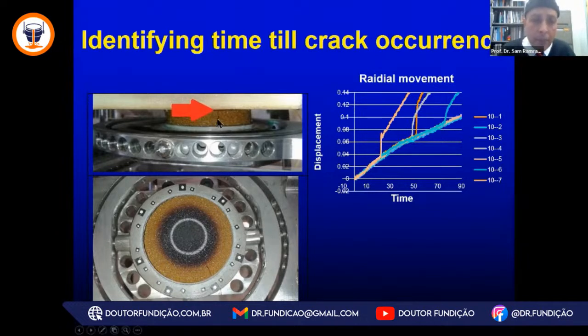Certainly, I mentioned the ideas of cracking. Here I'm showing you the crack propagation radially, and on the top view of the specimen, here is that crack. We can tell from the thermal distortion where we see this inflection on the curve, the time that that crack occurs. The main thing that we have to understand is not the fact that the specimen can crack, but we need to understand from the simulation activities that we run for our casting simulation when that alloy will skin or when it will freeze relative to the crack propagation.